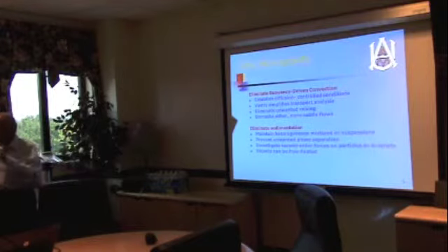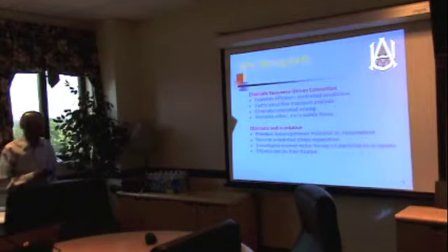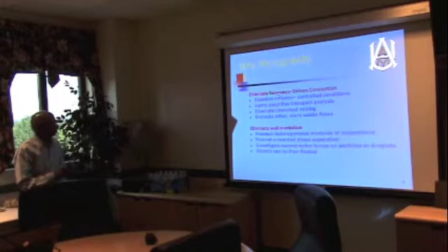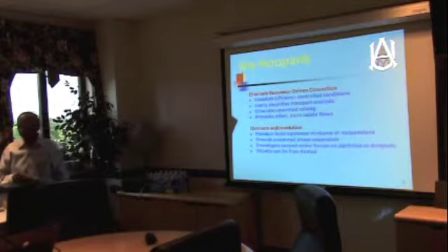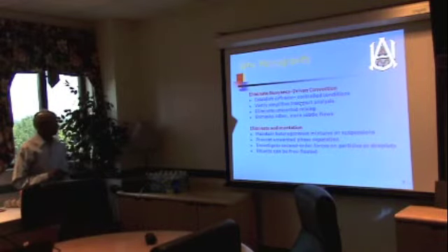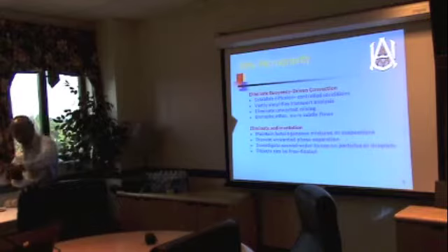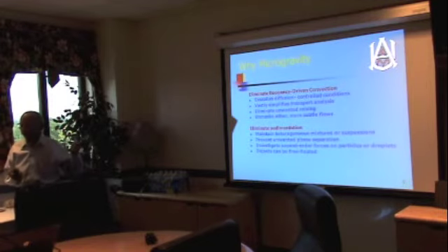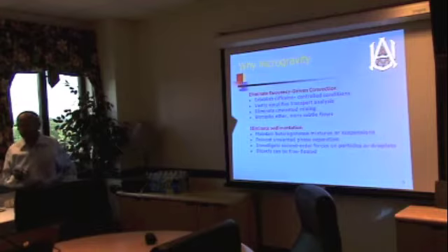And we can attain the Grashof number which gives you streamline conditions. Not any buoyancy. Not any turbulence. Because the Grashof number determines the turbulence in the fluid mechanics. So once we go to a g level which is low, one can do that. That is one of the reasons. So if you look at the number one thing in space is we eliminate the buoyancy driven convection. The convection effects are reduced. Never zero. But they are reduced. We establish a diffusion control condition. On ground, if you do any experiment, crystal growth experiments, we have two things competing. One is the gravity which brings the fluid down. One is the diffusion. And you cannot eliminate either of the two. But in space, one can eliminate or reduce the convection to a great level. So then we can establish a diffusion control.